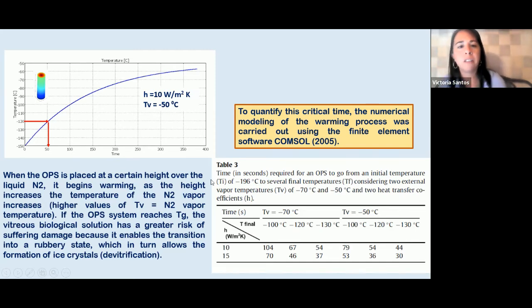We made several predictions for different temperatures and two different H values. And these are the times in seconds of these critical times that are very important to know when we lift samples.